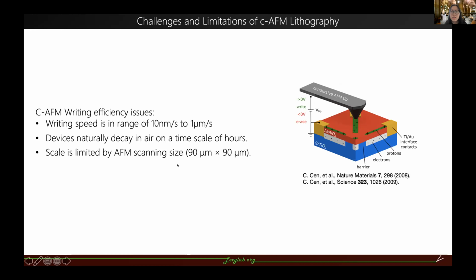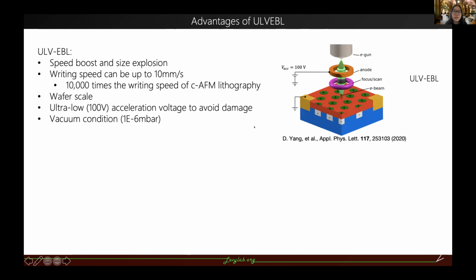So these conditions make conductive AFM sufficient for us to explore one-dimensional devices, but not when we want to expand to two dimensions. It's not enough for us. So to overcome these limitations, I would like to introduce ultra-low voltage electron beam lithography, which can also be used to pattern nanostructures at the interface. But at the same time, it introduces a speed boost and size explosion of the writing process. The writing speed can be up to 10 millimeters per second, which is 10,000 times the writing speed of conductive AFM lithography, and the size can be as large as a wafer.